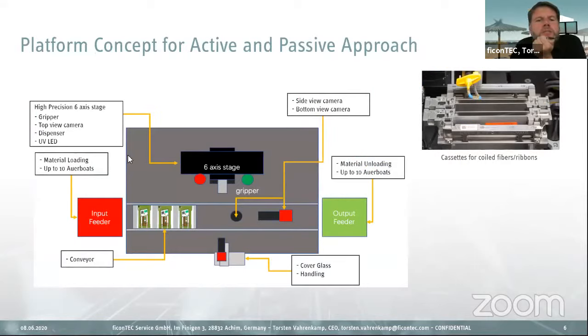If you see one of those systems, and this is actually a sketch of a machine, this is how it looks inside. There's a 6-axis alignment stage where we actually grip the fiber. It needs to be aligned in 6 axes. You have an input feeder, and a system where the chips are fed in. You have a conveyor where the components are traveling through. When you have an active alignment process, you have an auto fiber connect where you plug the input fiber or the outgoing fiber, or you're handling the cover glass for the passive attach. And if you have longer fibers, you need a cassette for coiled fibers.